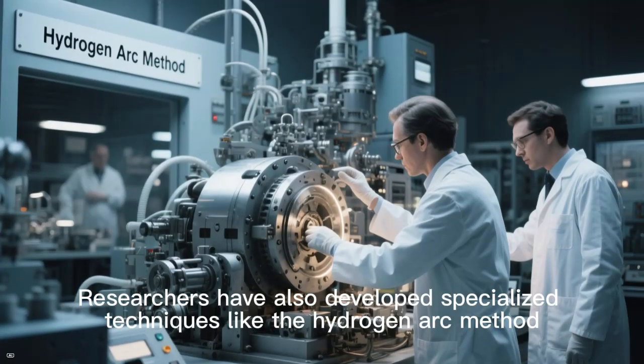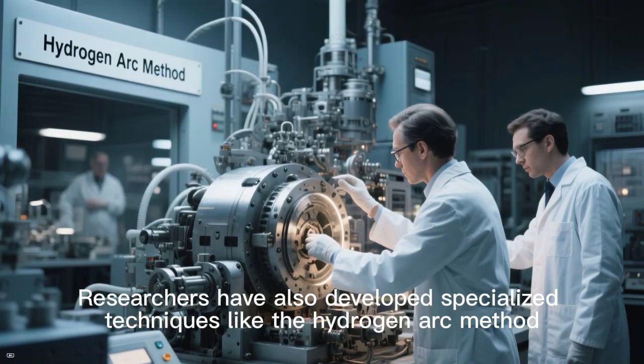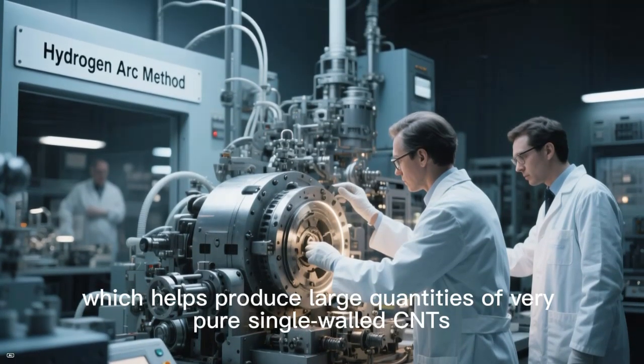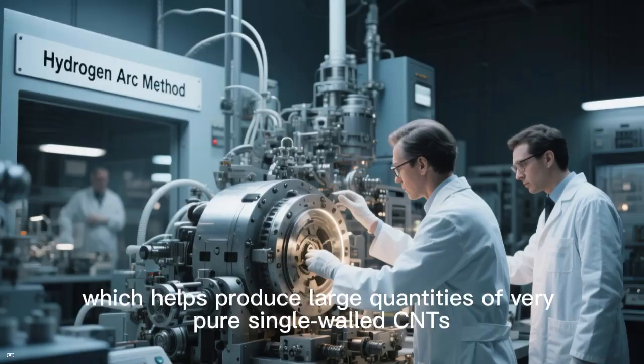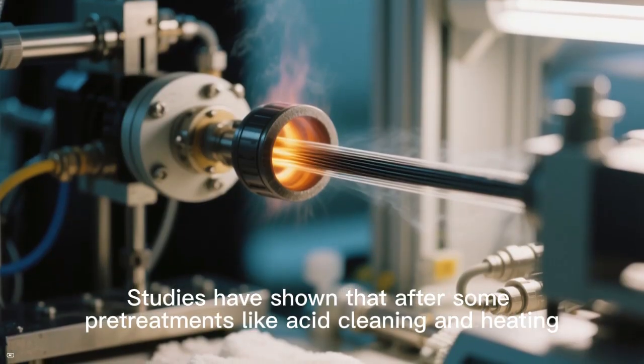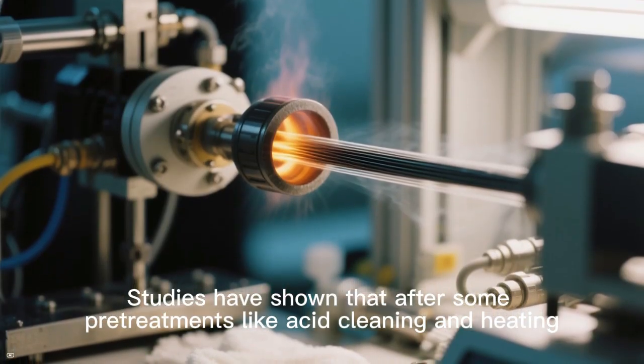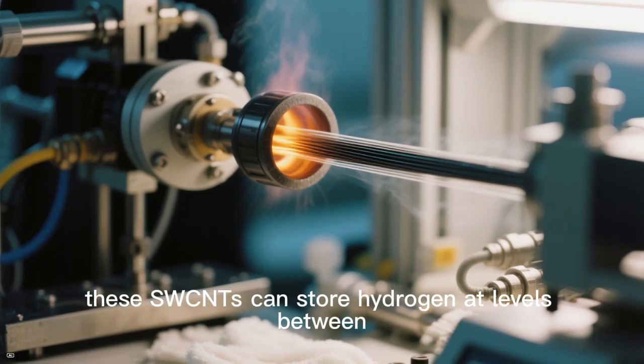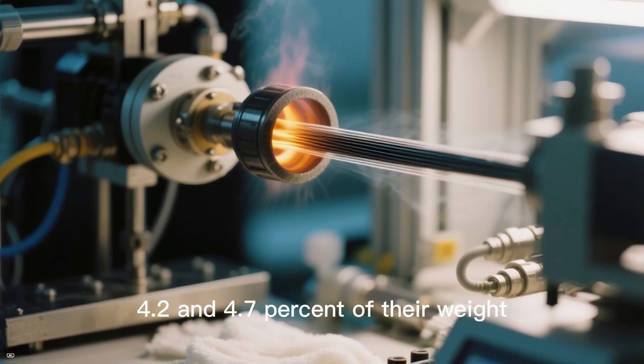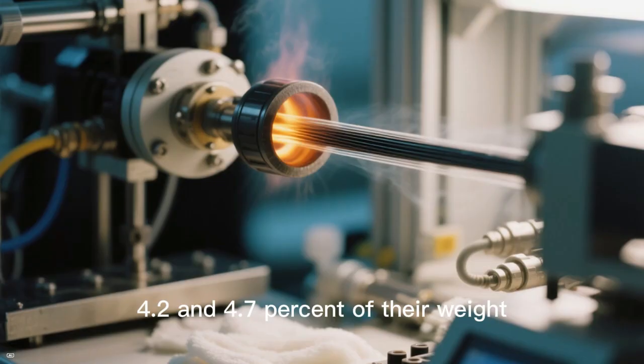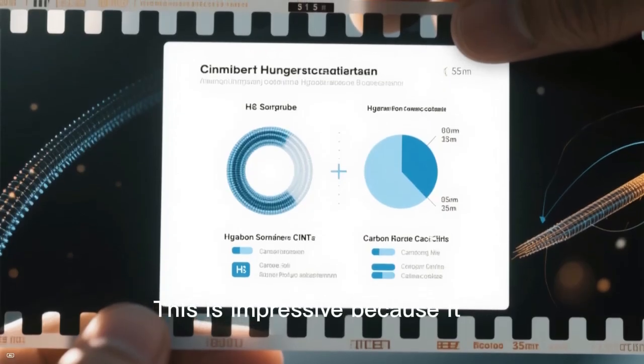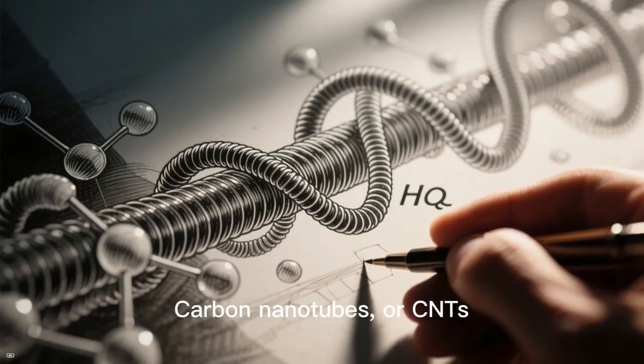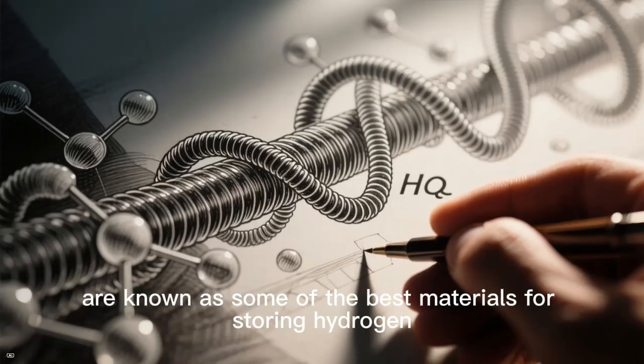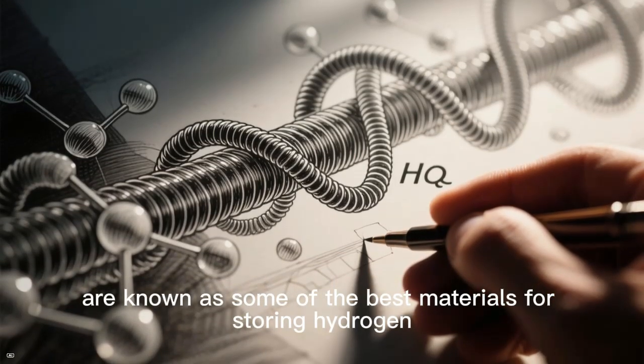Researchers have also developed specialized techniques like the hydrogen arc method, which helps produce large quantities of very pure single-walled CNTs. Studies have shown that after some pretreatments like acid cleaning and heating, these SWCNTs can store hydrogen at levels between 4.2 and 4.7% of their weight. This is impressive because it is about 2 to 3 times better than the hydrogen storage capacity of some metal hydride materials. Carbon nanotubes, or CNTs, are known as some of the best materials for storing hydrogen.